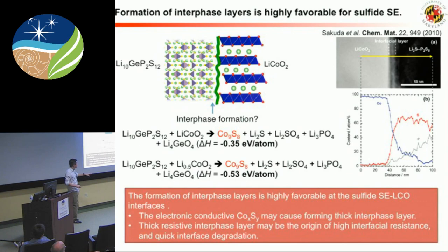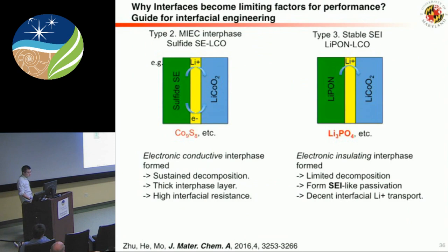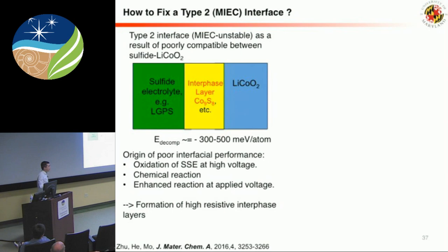This is also confirmed experimentally. As you can see, when they put these together, they form a new interface phase layer down there. So this is also going to be a potential problem for solid state batteries, because once they react, they form thick interface layers. And these are not as lithium conductive as the LGPS, so they will give you very high interfacial resistance.